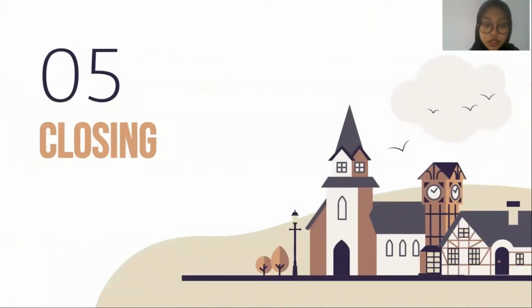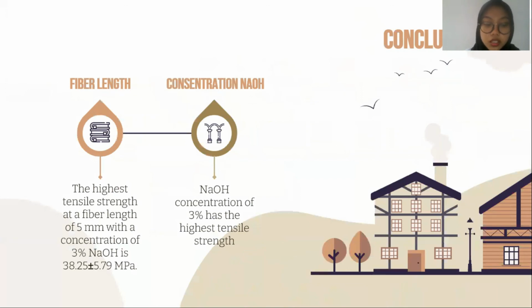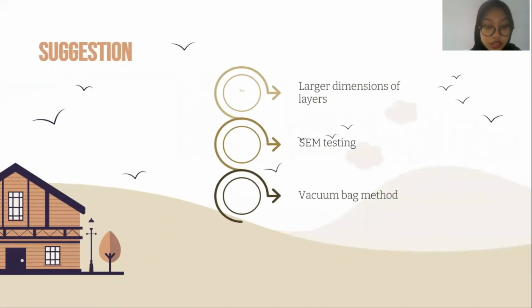And the last chapter is about closing. This is the conclusion of this research. The highest tensile strength is in the composite with a concentration of 3% natrium hydroxide, and the fiber length with the highest tensile strength is 5 millimeters. The following slides are suggestions for further research. First, use a layer with a larger dimension. Second, micro-observation such as scanning electron microscope or SEM should be carried out for the composite. The last is using the vacuum bag method to minimize voids that occur.